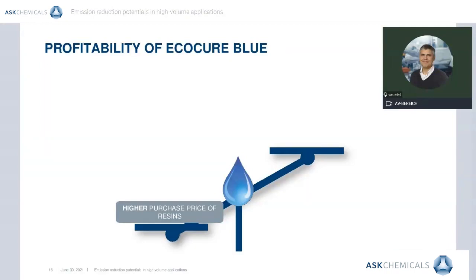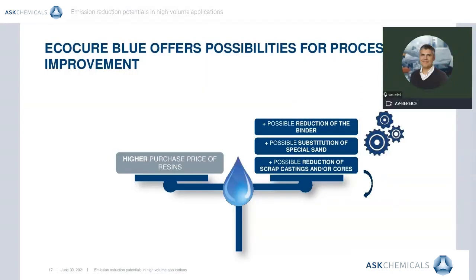Okay, the EcoCureBlue is often more expensive than most of the other systems on the market. The reason is that the production time is a little bit longer because we have to remove the free phenol in a much more drastic way. Furthermore, the solvent selection is much more restrictive than for the standard products because, in order to optimize the percentage of use, we must be sure that the consistency of the quality of the binder we are delivering is perfect.